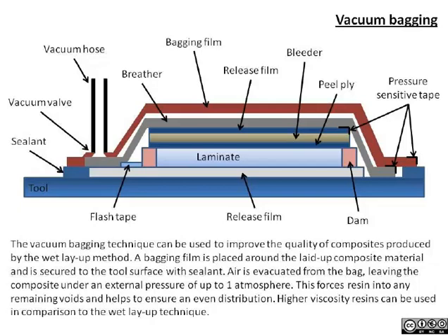If we need more than 1 atmosphere of pressure, we have the option of placing all of this in a hydroclave, where we can use the incompressibility of a fluid applied over the top of that vacuum bag to basically ramp up another state variable, increase our pressure, something that we haven't really discussed as a processing state variable till now, but this would be one example where we would not work at 1 atmosphere of pressure if we needed the high pressure from a hydroclave.